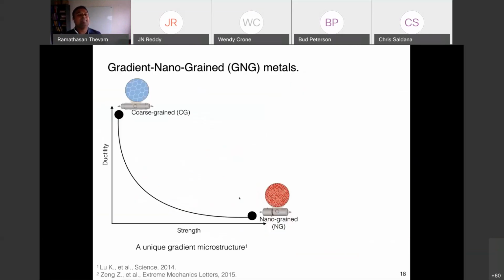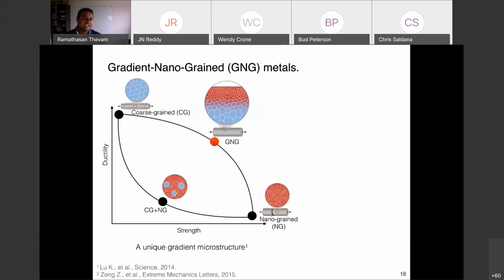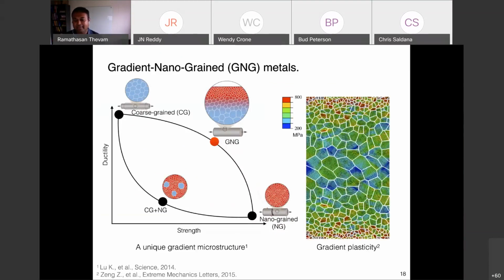This is something we have done to study a system called gradient nanograin metals. Nanograins have been shown to increase the strength of metals, but they reduce the ductility dramatically, so it can cause catastrophic failure of the material. Mixing the grains didn't improve the properties beneficially, but if you can create a spatial gradient in grain size, going from nanograins to larger grains, it can engage something called gradient plasticity that is due to the grain sizes associated with the Hall-Petch relation, where the strain will localize differently in different grains. So this leads to a progressive yielding situation where you can improve both strength and the toughness of metals.